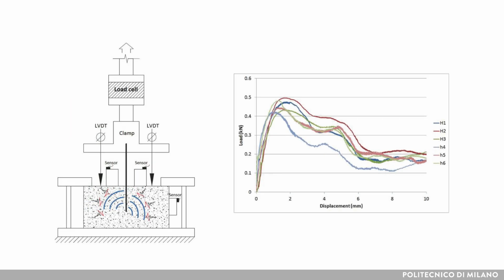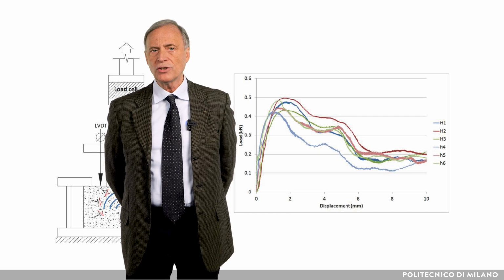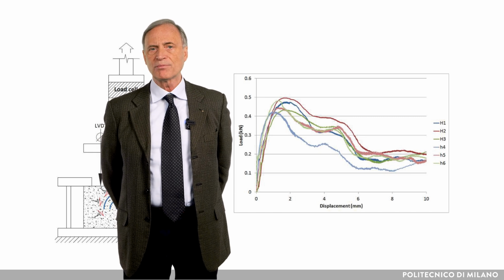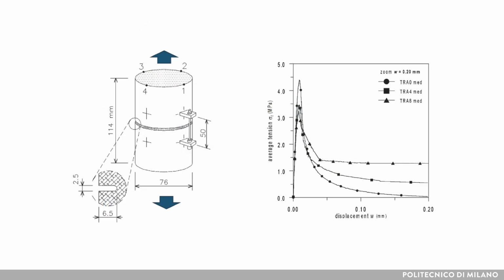The residual strength after cracking is due to the bond between the fiber and the matrix in the pull-out action. Even if we adopt a straight fiber embedded in the same concrete mix, the residual strength shows a certain scatter due to the distribution of aggregates around the fiber. The high standard deviation in the response is one of the peculiarities that has made difficult the evaluation of the fiber residual strength in the post-cracking. In a uniaxial tension test carried out on a notched cylindrical specimen, fiber pull-out contribution corresponds to the tail after the crack opening. Only the accumulation of fiber pull-out resistant mechanisms can give a significant contribution to the overall response after cracking.